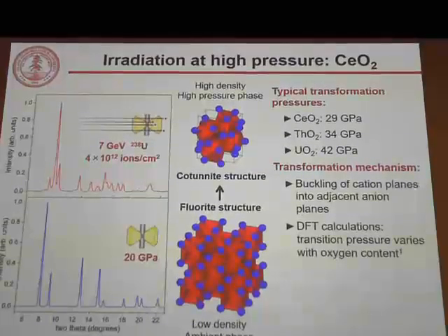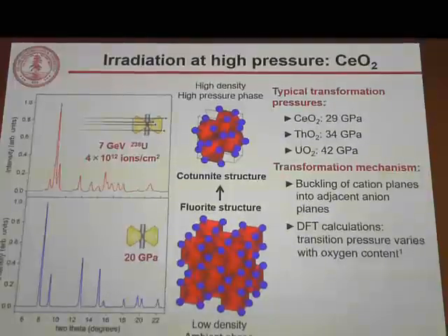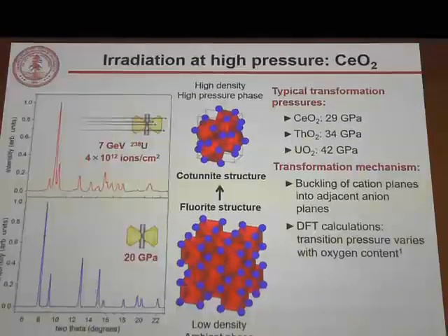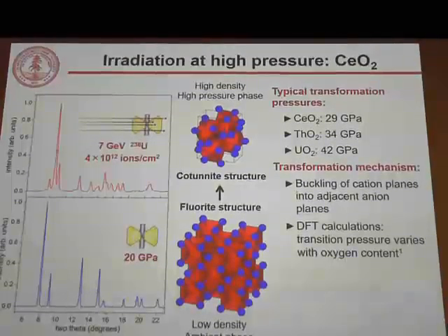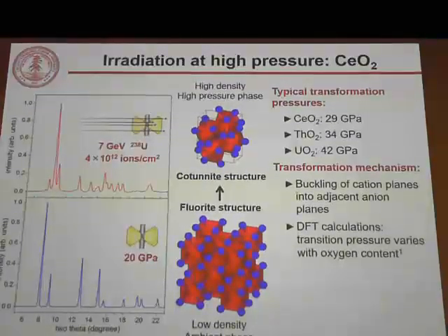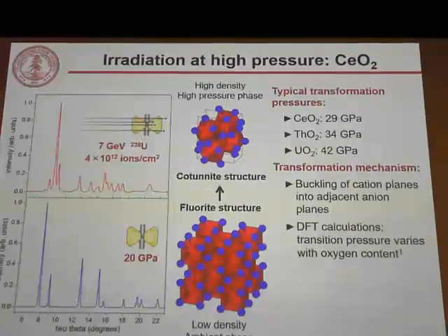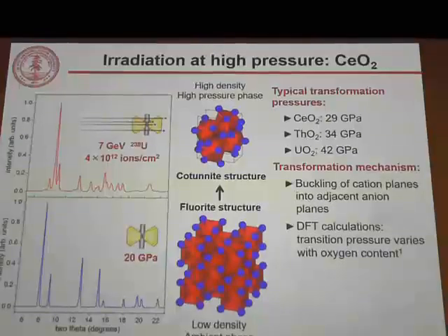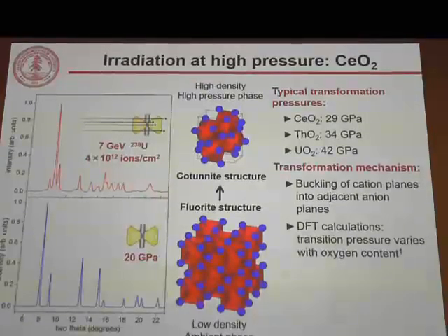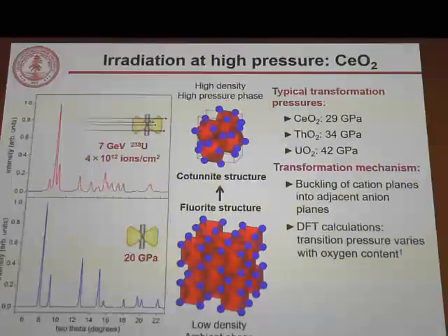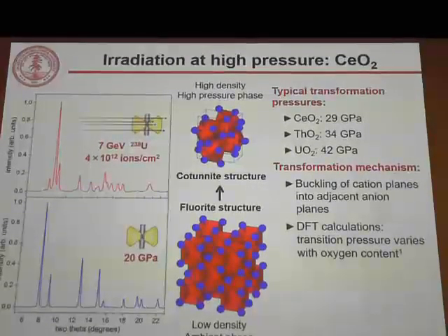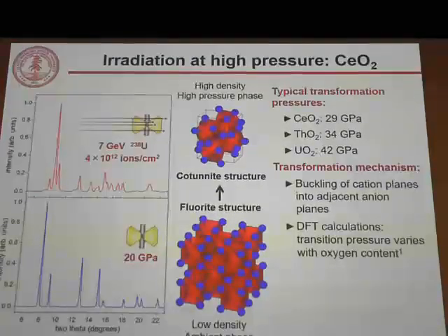And this is interesting because this is a typical high pressure phase of these dioxide materials, but it typically only forms at pressures far beyond that which we used in this experiment. For cerium dioxide, it's about 30 GPa, even higher for thorium and uranium dioxides. If we look at the transformation mechanism, we know that it involves the buckling of fluorite cation planes into adjacent anion planes. So we might conclude, therefore, that anion rearrangement, as we have seen in the last few slides, is induced by swift heavy ion irradiation, might have a strong influence on this transformation.